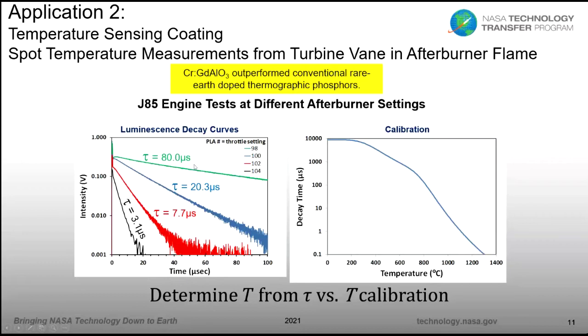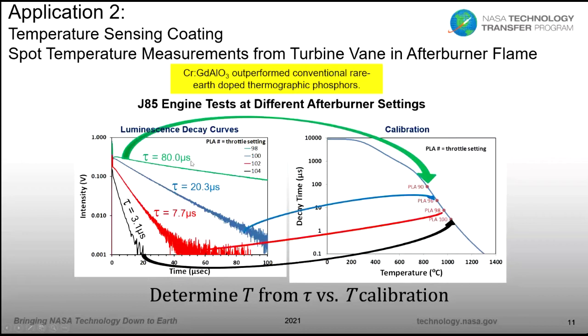Then to get your temperature at each setting, all we do is determine the decay time, for example, 80 microseconds, go over to our calibration measurement, see where 80 microseconds would be about here, run over to our calibration curve, and the point we meet over here gives us what the temperature is. In this case, 830 degrees C. If we do that for all the decays, we see that the temperature at that spot ranges from 830 to 1027 degrees C as we change the afterburner settings.